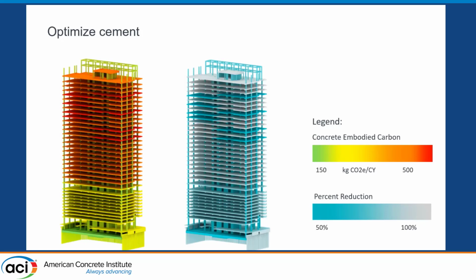So if you're looking at this graph here, you can see that the percent reduction of cement for columns and foundations, and then the shear walls, for example, it's very high. You can see that kind of dark teal color. And that's because their strength gain was delayed. So they were able to use supplementary cementitious materials such as fly ash and slag, which sometimes can delay strength gain, but can replace cement and ultimately lead to higher strengths, but just not right away.